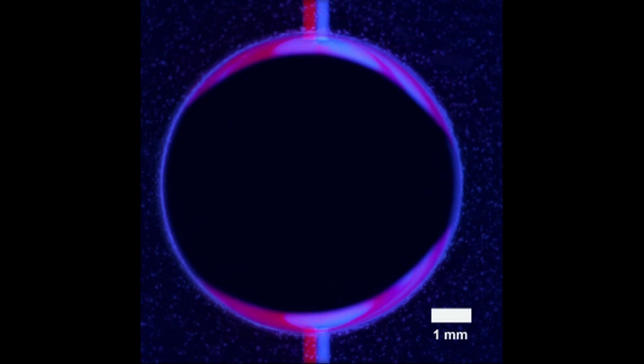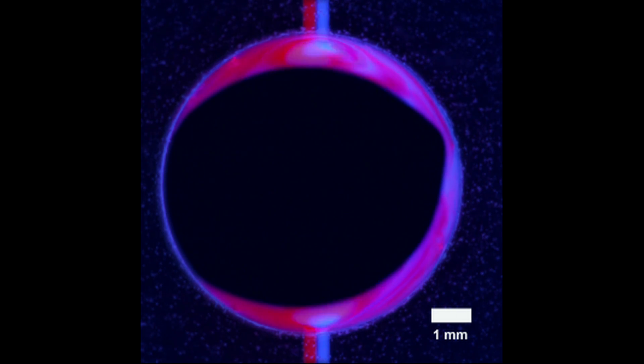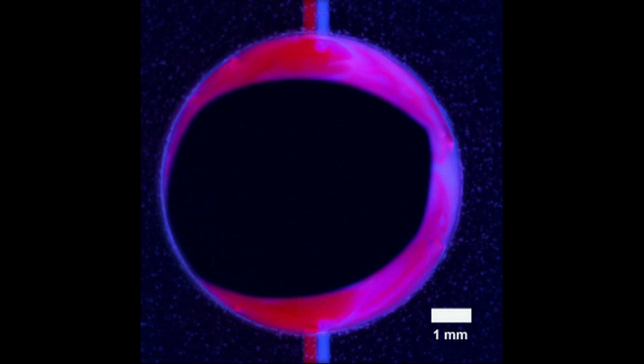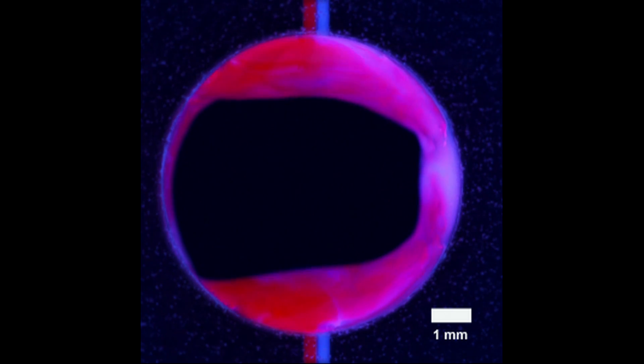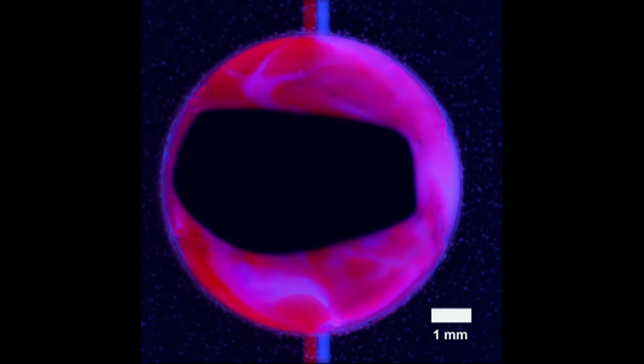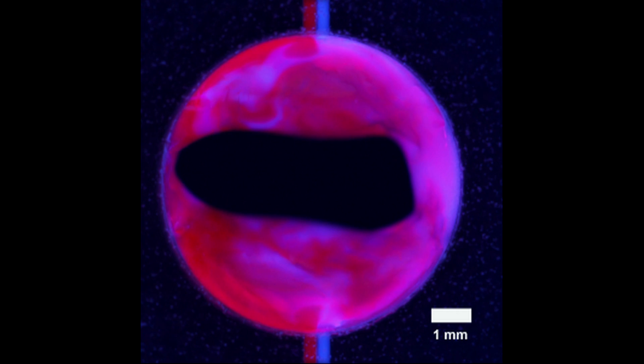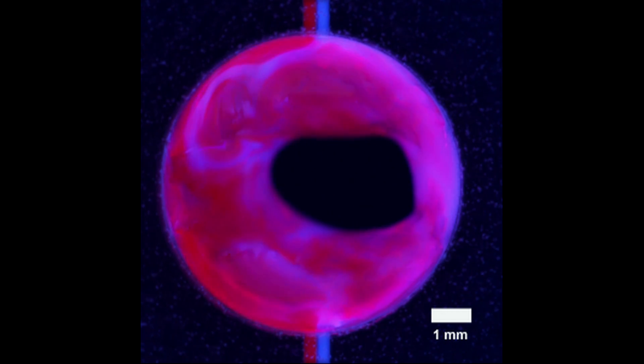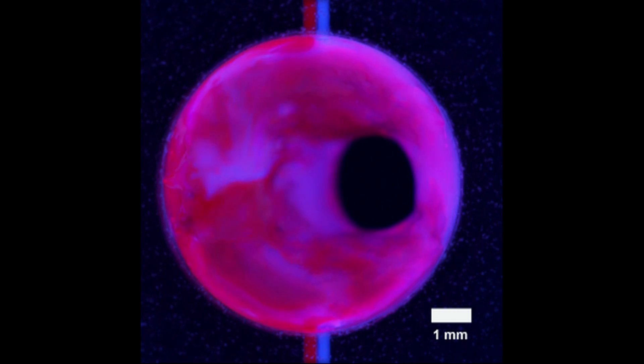In this example, you see an 8mm hole and two fluid streams are entering that hole. One we've dyed red with a fluorescent dye and the other is actually light blue. And so you see the interface that develops between those fluid streams as it's pumping into the hole. It folds and folds and folds on itself, and you start to see the mixture of those two fluid streams filling up the entire hole eventually. And then at a later time, it will actually harden into a structural polymer.